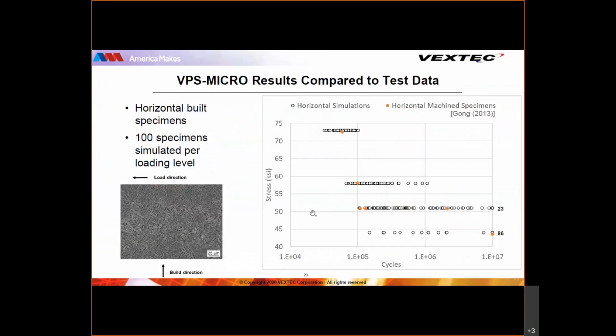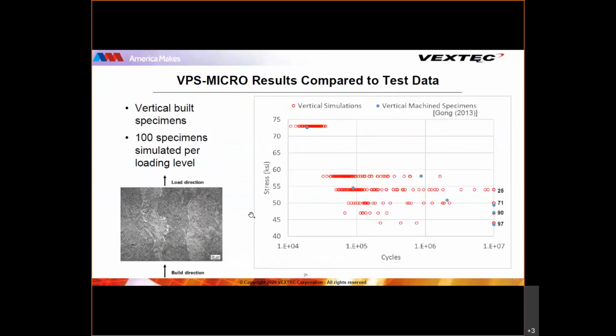And here you see the updated simulation results for the horizontal EBM condition compared with some published fatigue test data here in orange for the horizontal build EBM Ti-64. And as a reminder, the image of the horizontal EBM microstructure that we previously showed is here again in the bottom left. And we'll also show updated simulation results for the vertical EBM condition, compared again with published fatigue test data for the vertical build EBM. And the image of the vertical EBM microstructure again is provided here. And so the model in both of these cases is showing good agreement with the limited physical testing data there is.